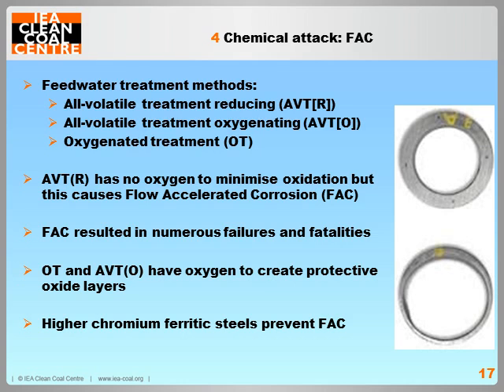Feed water for the steam cycle can be treated in two main ways. Firstly, deoxygenated feed water, and secondly, oxygenated feed water. Deoxygenated feed water results in no steam side oxidation, but the treatment method can dissolve iron in some situations. This is known as flow accelerated corrosion and causes a thinning of the pipes. Flow accelerated corrosion has resulted in numerous failures and fatalities historically. Despite this, deoxygenated feed water is still used in over 70% of fossil fuel power plants today.